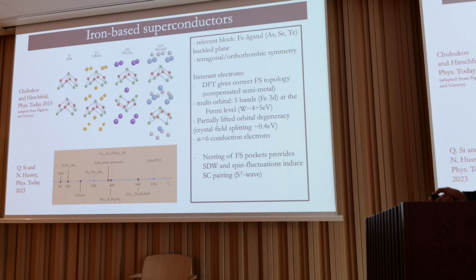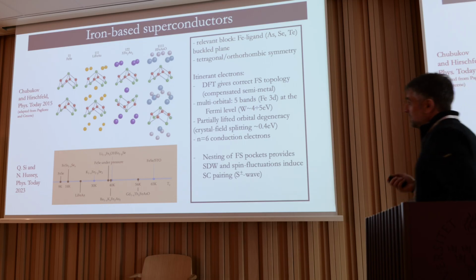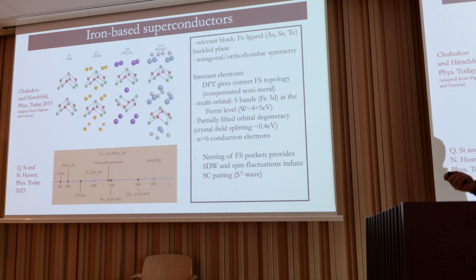There are many families, and these families have only the iron plane with ligands above and below as a common block—these can be chalcogenides or pnictides. They have high TCs on the order of 30, 40 to 60 Kelvin, many of them, and they basically have tetragonal symmetry or some orthorhombic distortion. If you do DFT, you get more or less the correct Fermi surface topology, a semi-metal compensated with hole pockets and electron pockets, with mainly 5 bands coming from iron 3D orbitals at the Fermi level.